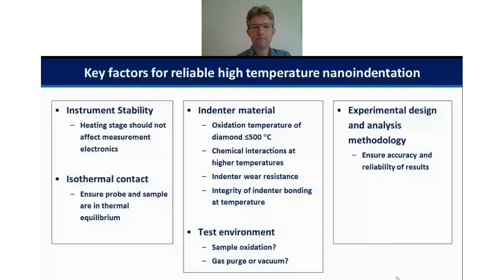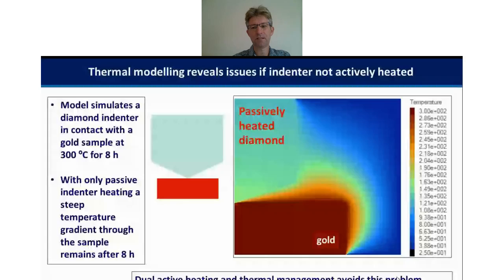And the final thing that we really need to consider is that in high temperature tests, typically we can get a lot more time-dependent deformation, or viscoelastic and viscoplastic deformation, and how we cope with that in the test design and also the analysis methodology is quite important. I'll give examples of how we can mitigate this in our testing to achieve high quality creep data and also high quality elastic modulus data.